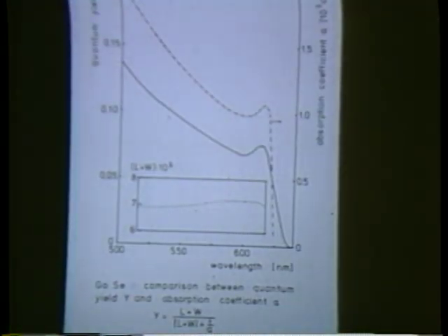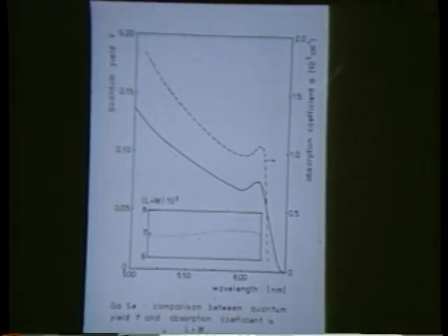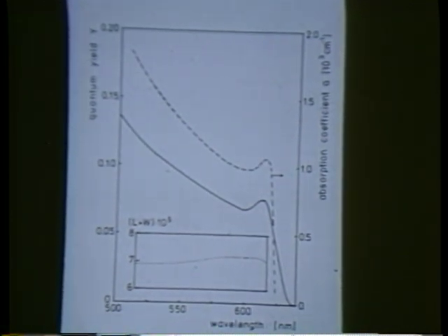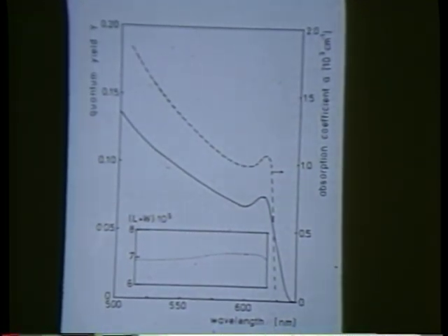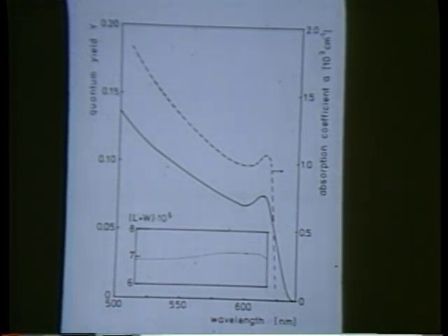I want to give you, as an example, measurements at gallium selenide. This is a p-type semiconductor. And here is the absorptivity. It's relatively small, as you'll see. Therefore, the light penetration is rather deep, and the yield is rather low. And in this range, where yield is low, this formula is well applicable. And so one gets a diffusion length in the order of 7 × 10⁻⁵ cm.